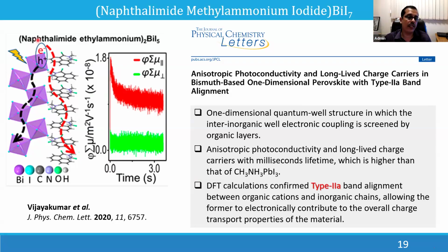So what we did is that we used a semiconducting material. Okay, so far nobody was using a semiconducting material as the organic cation, but we tried to incorporate the semiconducting material into the perovskite structure and see how much it can improve the electronic properties. Okay, so this is the material we designed. We were able to get a one-dimensional structure, and this organic part beautifully stacked, forming a well-defined structure. And when we studied this material, we were able to get a very high photoconductivity signal, because we did theoretical studies, and we found this organic component also contributing to the electronic structure of the material. Okay, that electronic structure contribution actually reflected in the photoconductivity, and we were able to get a significantly higher photoconductivity for this material.